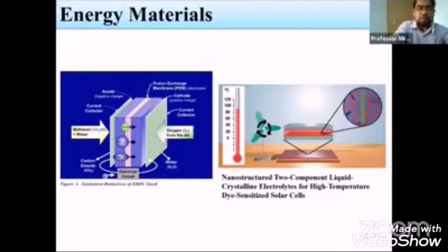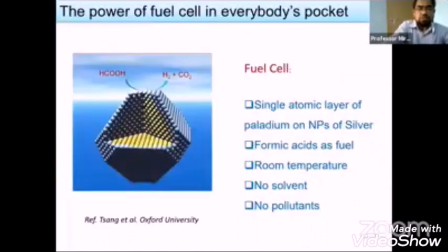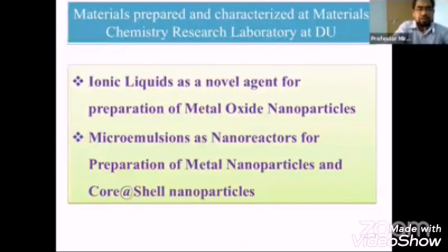People are continuously developing materials which are very interesting for the energy field. Here I am showing oxidation reduction of dimethyl ether. We need to develop new polymeric materials, new electrodes, and new catalyst materials which are alternatives to platinum. And fuel cells, we are using fuel cells even in our pocket. A single atomic layer of palladium on nanoparticles of silver, with formic acid as a fuel, can all be operated at room temperature. We are using no solvent, no pollutant, so it's environmentally friendly.